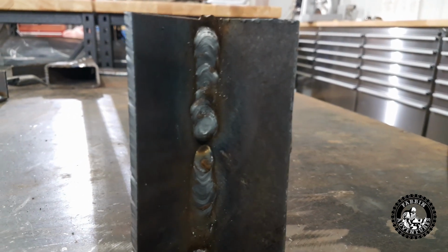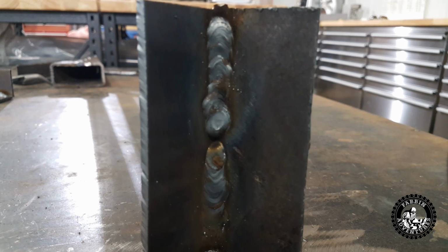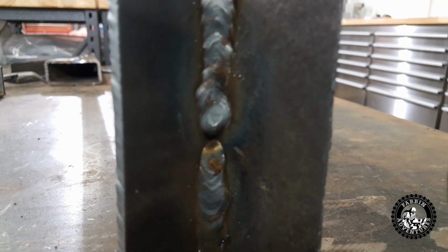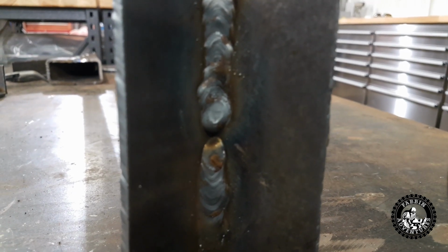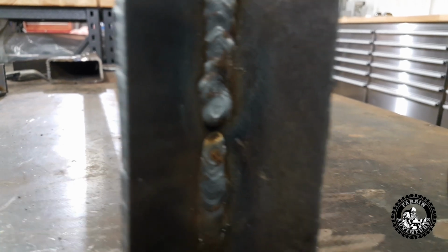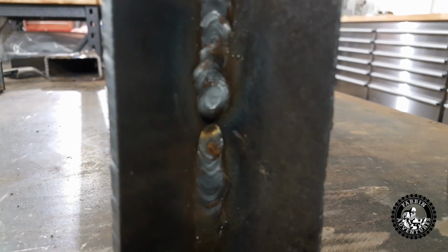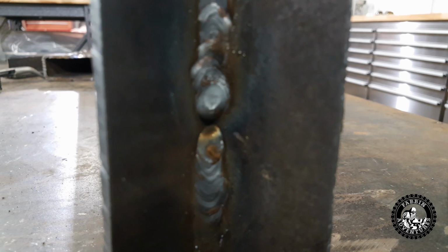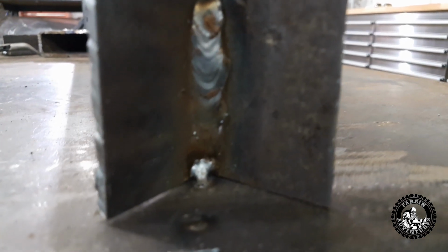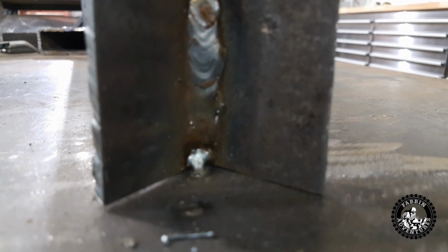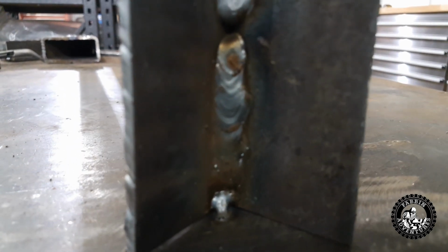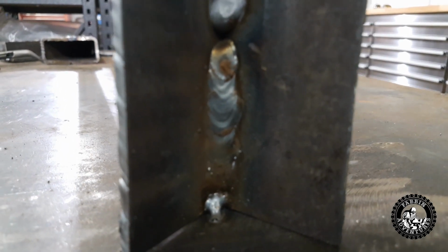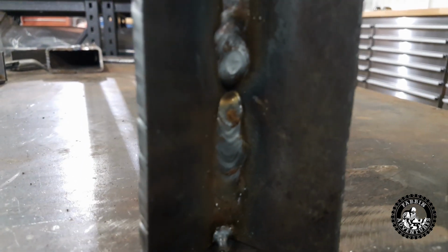And we go over and see the trouble she had. The downhand weld's a tough one to do. And what ended up, you can see the blob there. She wasn't dropping her U on the pattern fast enough and below the puddle, and the puddle was getting away on her. It was going down faster than she was moving down. And this one here was actually her first attempt, which doesn't look too bad, but it's still a really thick weld. Could have been moving a little faster.